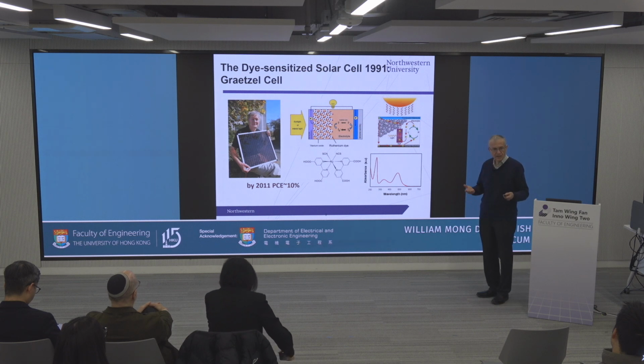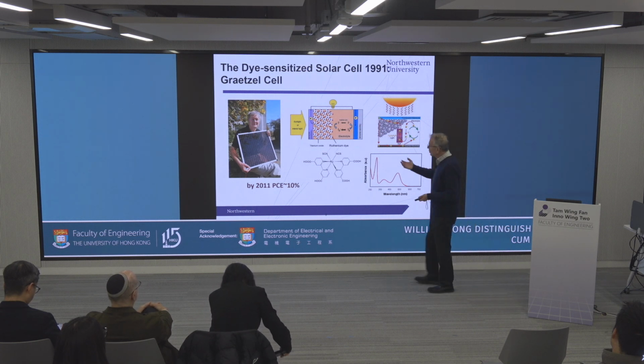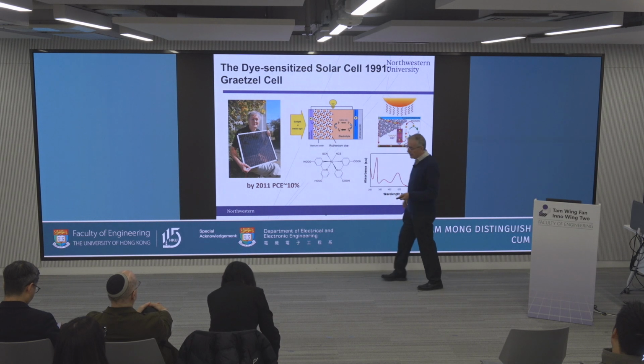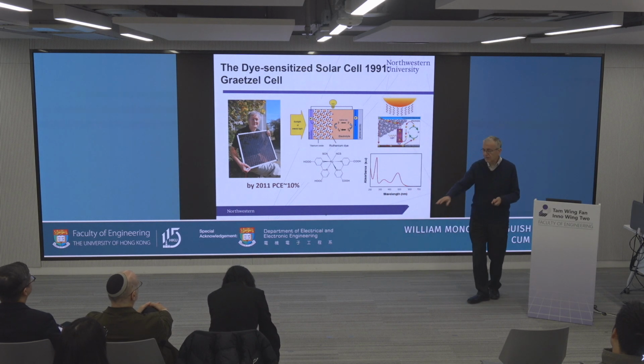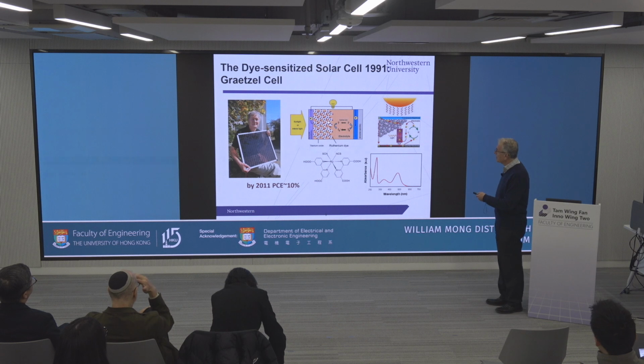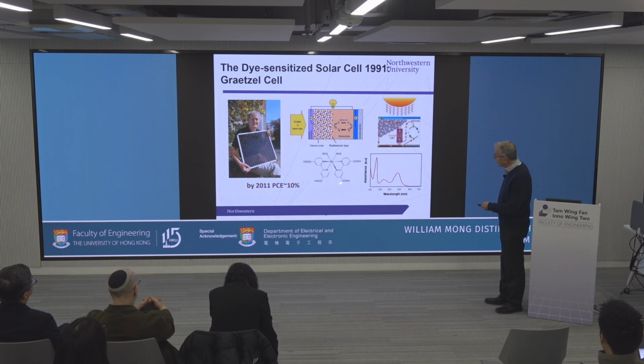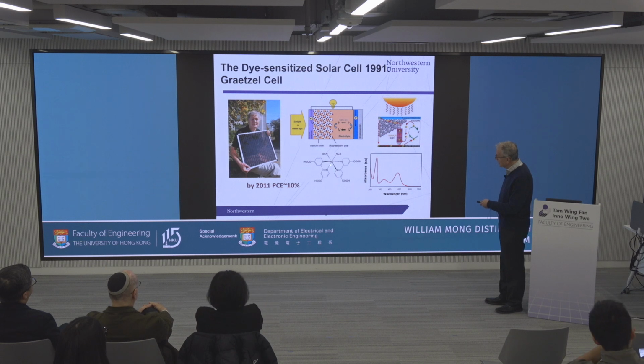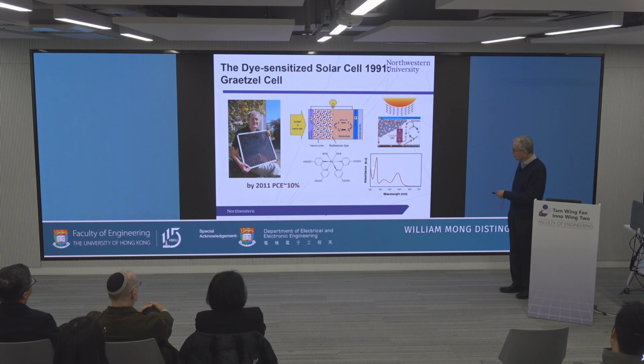It was made from chemistry, liquids and solutions and solution processing. And he took a film, a porous film of titanium dioxide, polycrystalline titanium dioxide film, and on it he attached a ruthenium inorganic complex that absorbs light, and it attached it by these carboxylates on the surface. And this is the spectrum of this material. So it absorbs some light, it's visible, like 560, here 350. It's not a lot, but it absorbs some light.